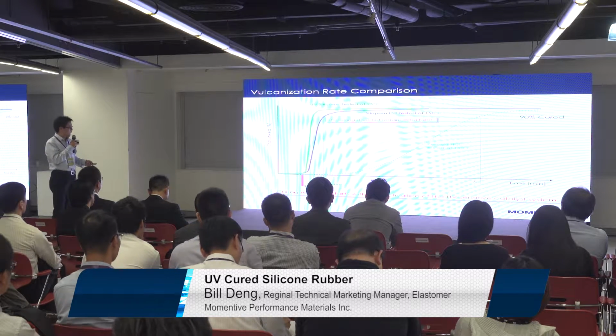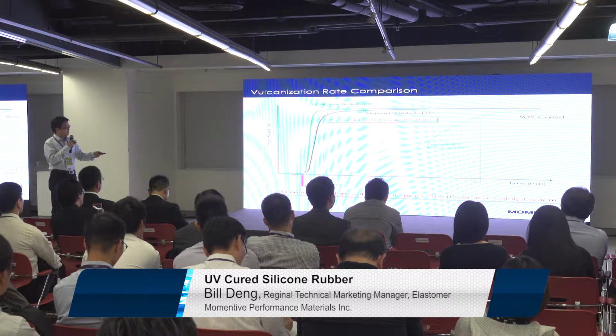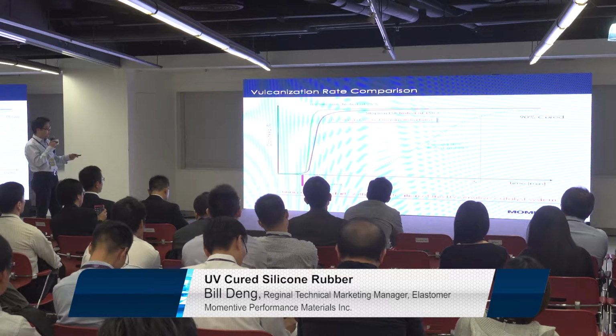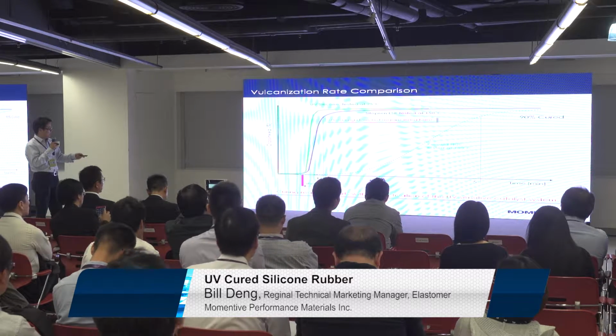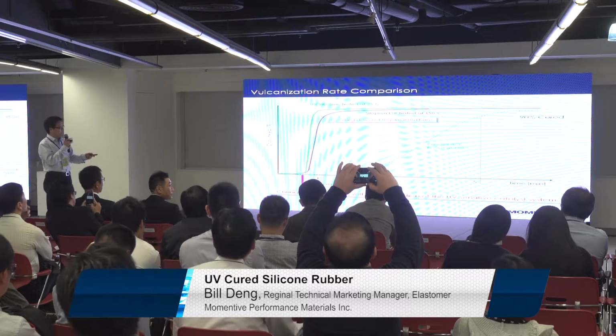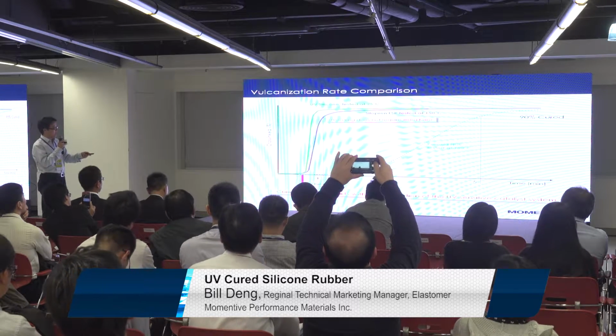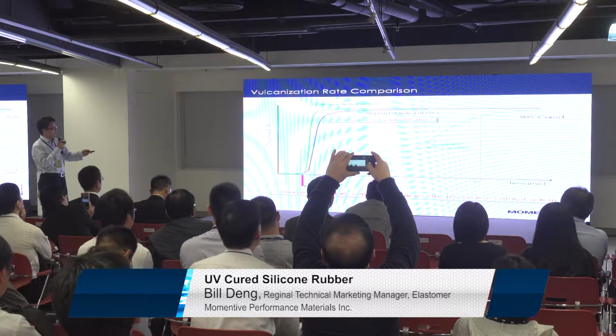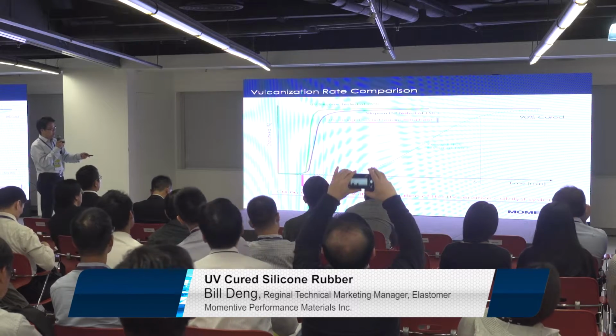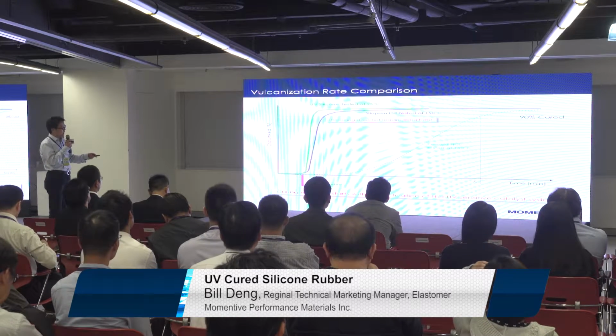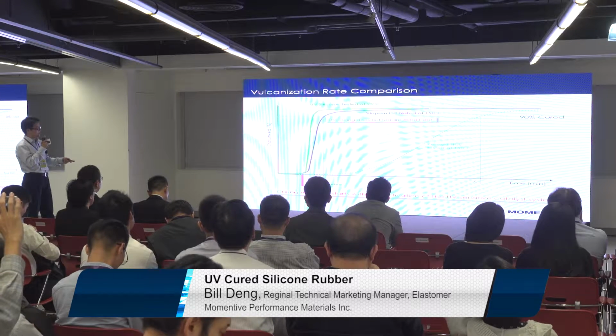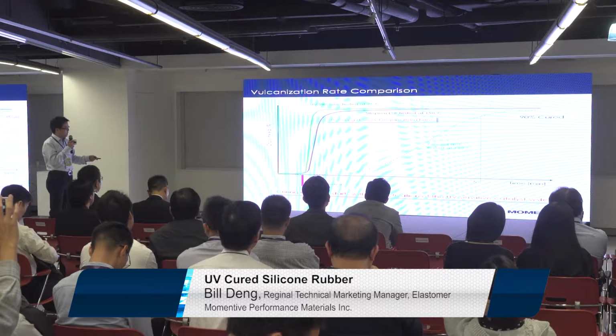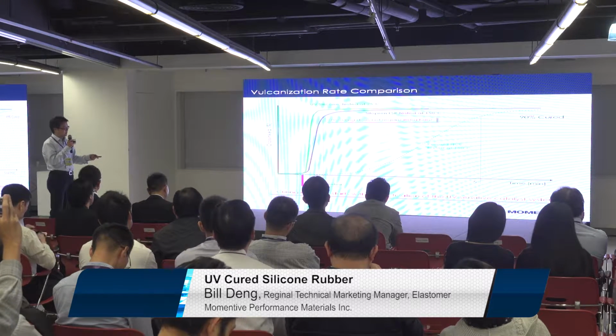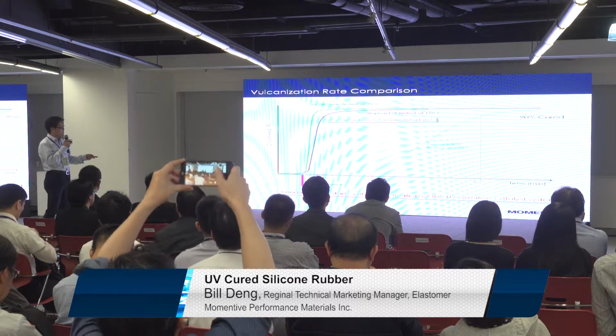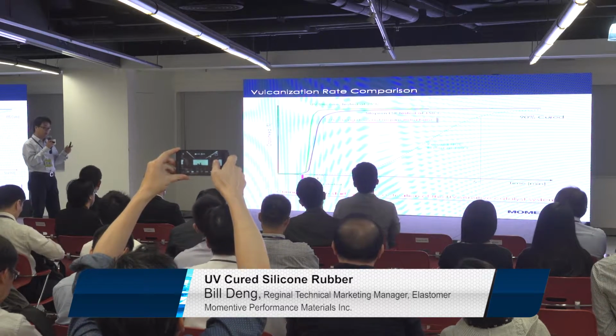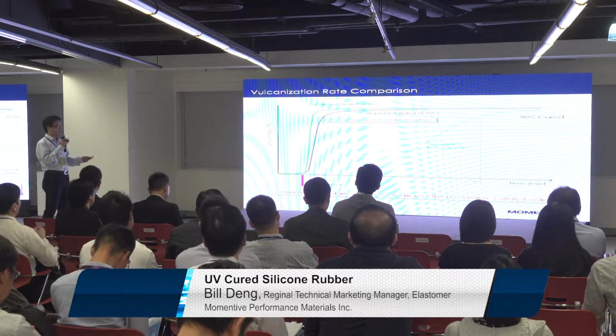There is a curve to show the different systems for silicone rubber to be cross-linked, over time. So we can see the first one is the peroxide HCR. It's tested at 150 degrees, and we can see it reaches 90% cured in almost 5 minutes or more than 5 minutes. For regular LSR, liquid silicone rubber with platinum catalyst, the ready-to-use LSR, it's less than 1 minute, but still needs some time. But for UV LSR, it's very fast. When you turn on the UV light, the cross-link just starts. So very quick, in a few seconds, it can be done.